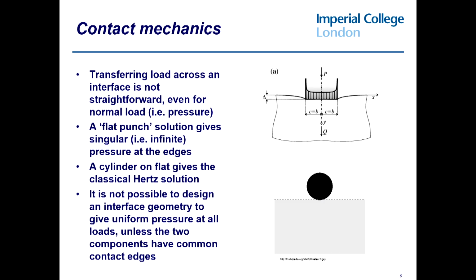Even if we take the simple case of a normal load, where we're simply transmitting pressure, it's quite difficult to design the interface without leading to concentrations of load and concentrations of stress. So, for example, if you take a flat punch and you press it down onto a surface, you might think that that would generate a uniform pressure. But in fact, what you would find is that there are stress concentrations at the edge, and indeed, if the punch is rigid, those concentrations become singularities. So pressure becomes infinite at the edge.